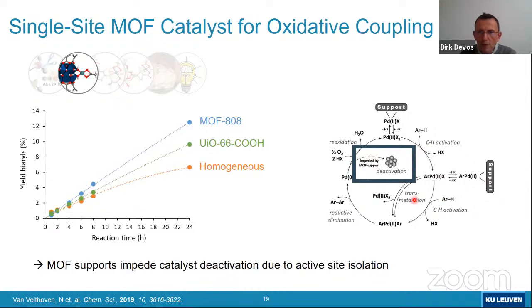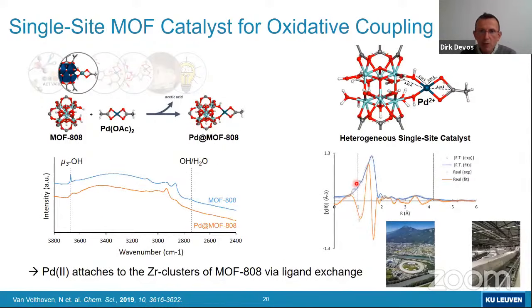So in this whole process, apparently the deactivation, which typically occurs at the stage where the palladium 0 is not efficiently reoxidized, it seems that the dispersion of the palladium over the MOF makes the reoxidation eventually easier so that you have less deactivation. We spent quite some time, and I'm not going to go into all the details, but we spent quite some time in understanding how the MOF is doing that. And indeed, this seems to be a case where just the cluster of the MOF stabilizes the palladium and binds the palladium. Let's look in a bit more detail.